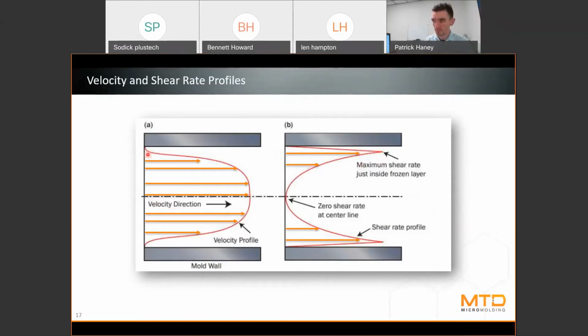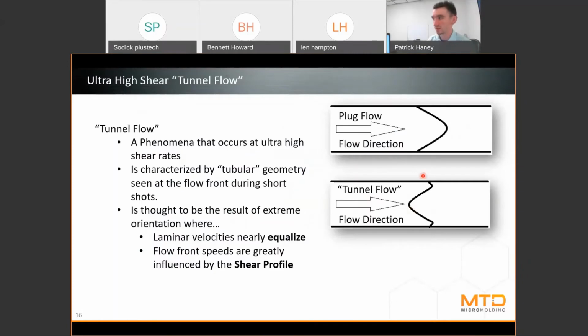So the velocities in the velocity profile tend to be the same length and the same speed, but we know that the shear rate is still highest closest to the mold walls, or nearly closest to the mold walls, right? Because out here we have the frozen layer, so there's no shear or velocity going on right against the mold wall. Then we have extra orientation, extra frictional heating, those types of things going on in these areas. So as we start to recognize this tunnel flow phenomenon, it starts to look an awful lot like that shear rate profile, doesn't it?